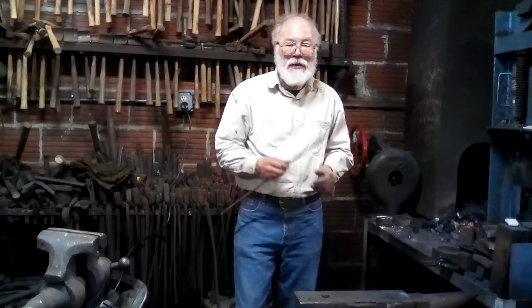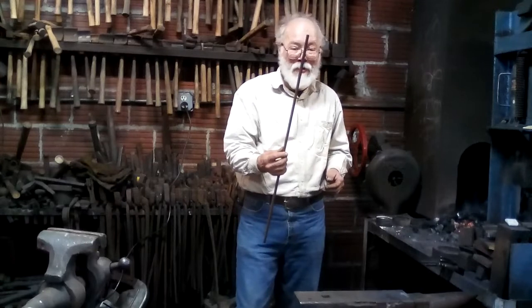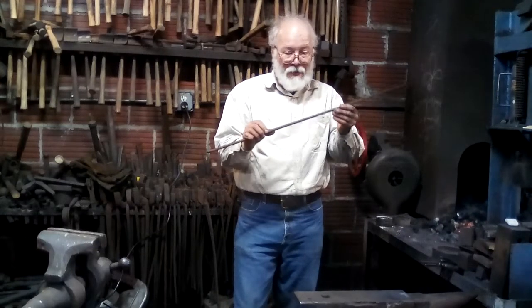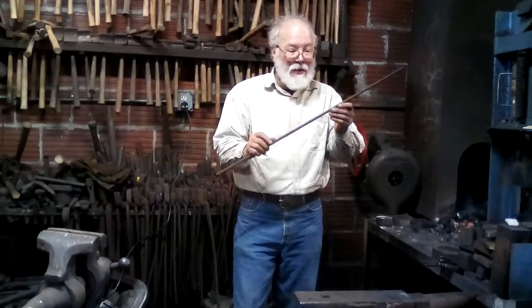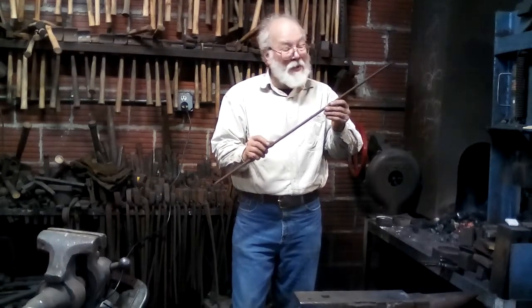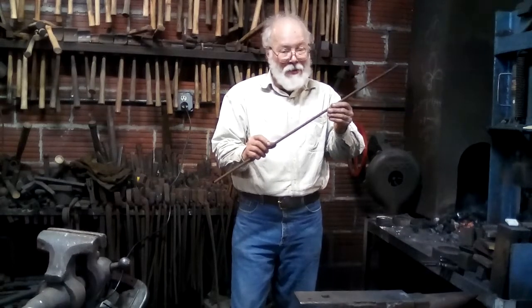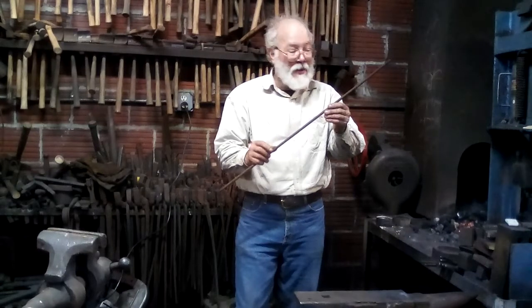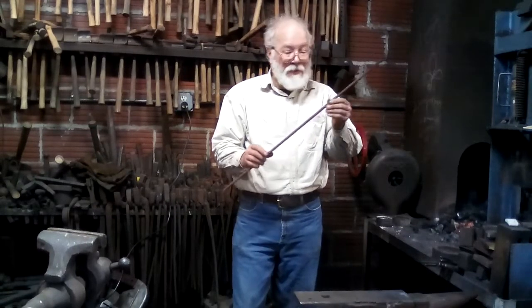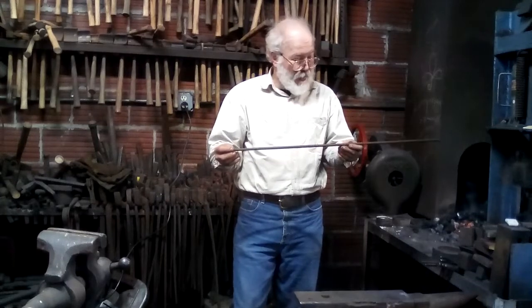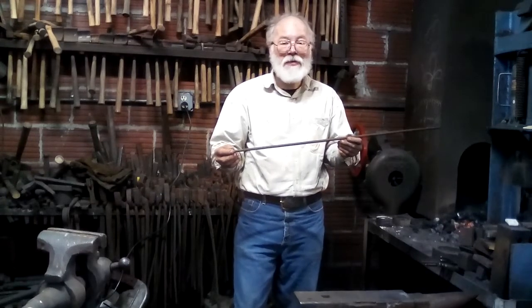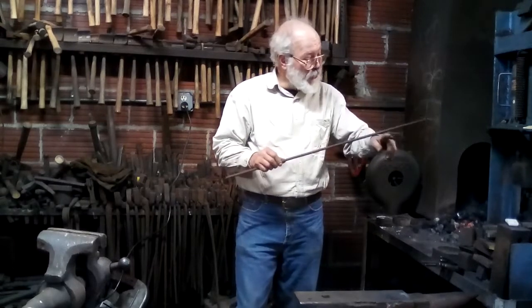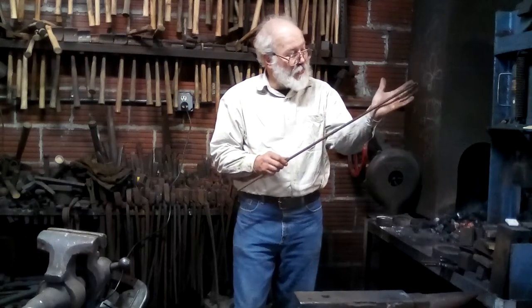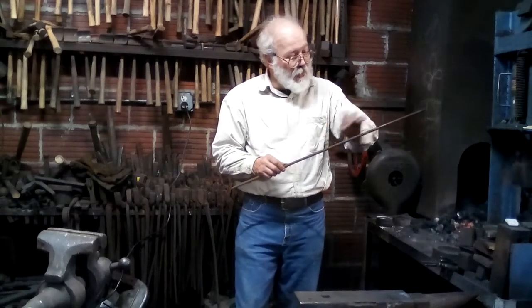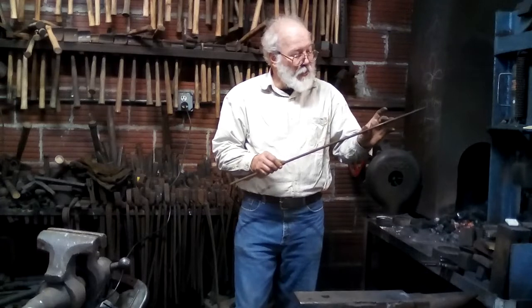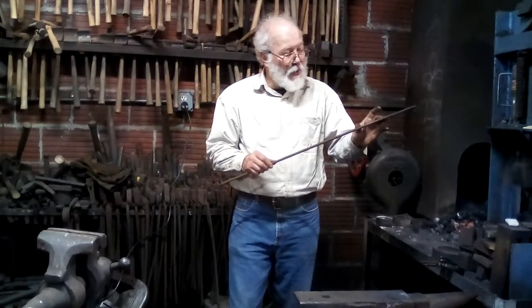In order to make this an easier first exercise in forge welding, we're going to start with a piece of stock that's not too small and not too big, so it'll be easy to heat up, but not so easy to burn up, because that's either getting it too cold or not hot enough, or too hot, and it either melts or burns up. So this is a piece of 3/8 inch stock, and it's long enough, about 2.5 feet long, so that I won't need a pair of tongs, so there'll be less complication. And what I'm going to do is hairpin this back and take about the length of my hand, about 7 inches or so, and turn it back on itself, and forge weld about 3.5 to 4 inches of that.